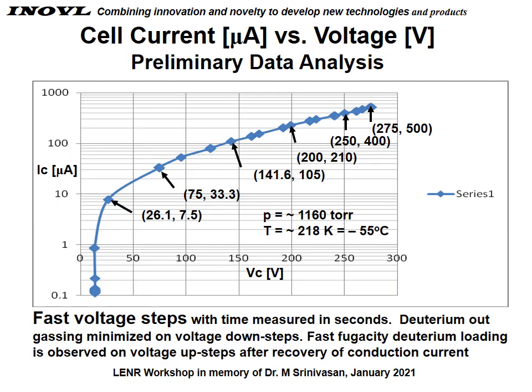Here's another plot of data. This is a semi-log plot of current versus voltage. And you see it was coming down in a nice, relatively straight line until it got to lower voltage, about 25 volts, and then it dropped precipitously. At the time, we thought, well, that was just our instrumentation. It was a roll-off that was associated with that. Later, we realized that no, there was something really going on there.